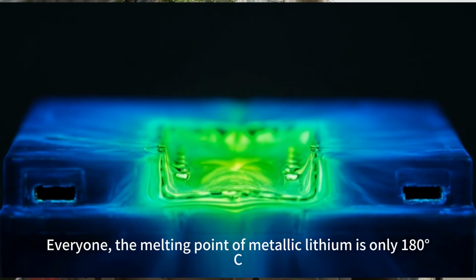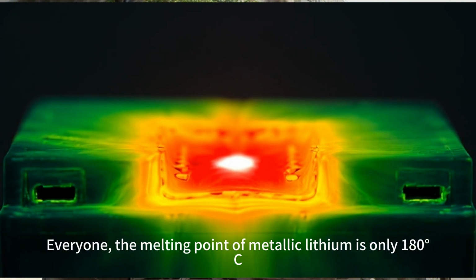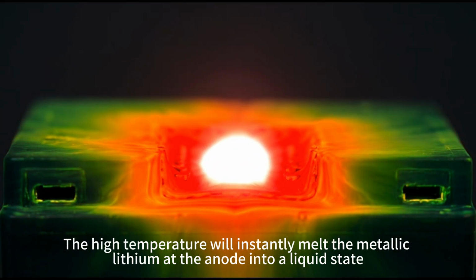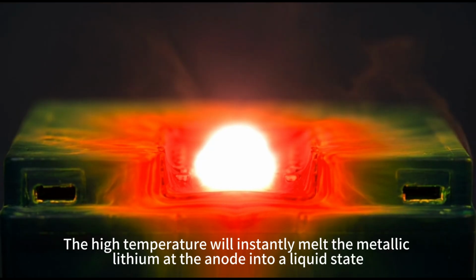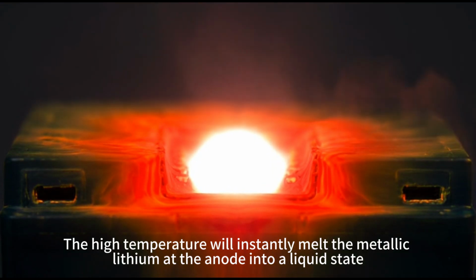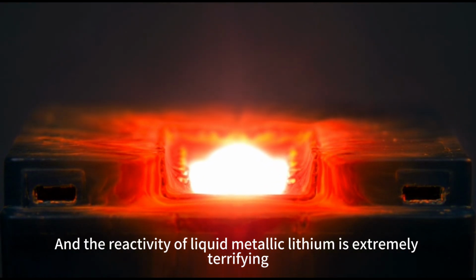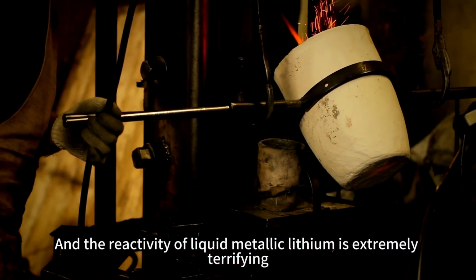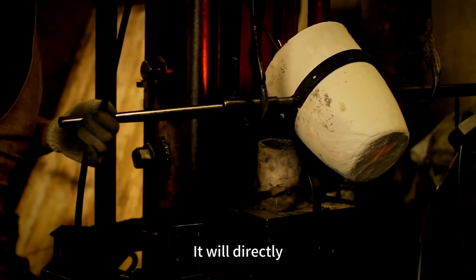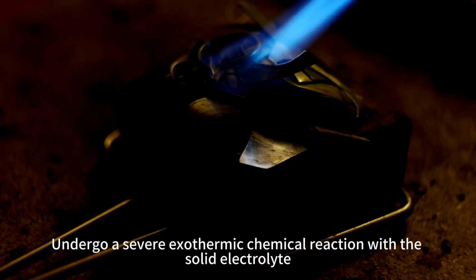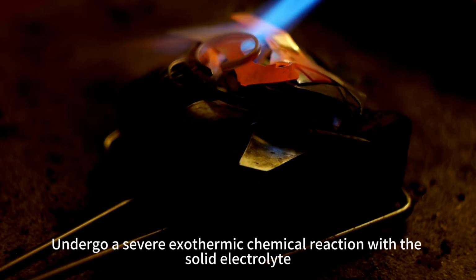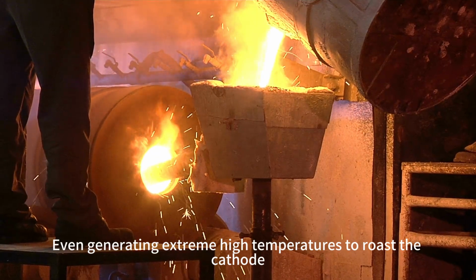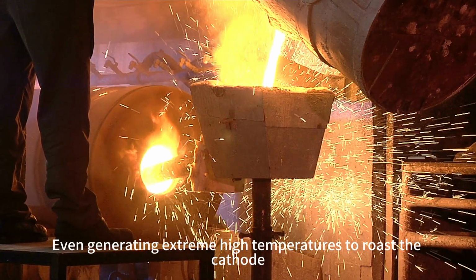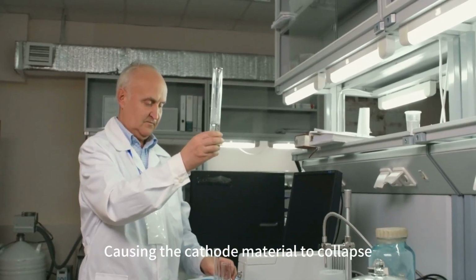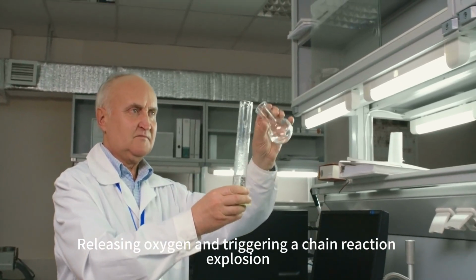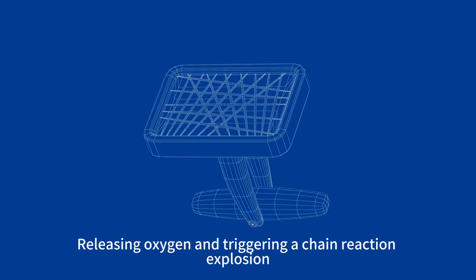Everyone, the melting point of metallic lithium is only 180 C. The high temperature will instantly melt the metallic lithium at the anode into a liquid state. And the reactivity of liquid metallic lithium is extremely terrifying. It will directly undergo a severe exothermic chemical reaction with the solid electrolyte, even generating extreme high temperatures to roast the cathode, causing the cathode material to collapse, releasing oxygen and triggering a chain reaction explosion.